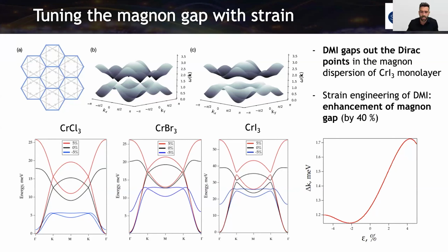Yeah, well, in this case, we don't have a substrate, so we are applying a strain to the lattice parameter, and we are allowing the coordinates to adapt for each step. So we are simulating a perfect, relaxed system. Exactly. And for example, in this case, we are doing uniaxial strain along the A and the B axis. And for the chromium trihalide it is biaxial.